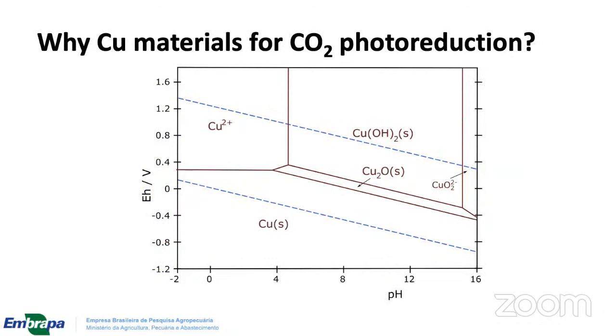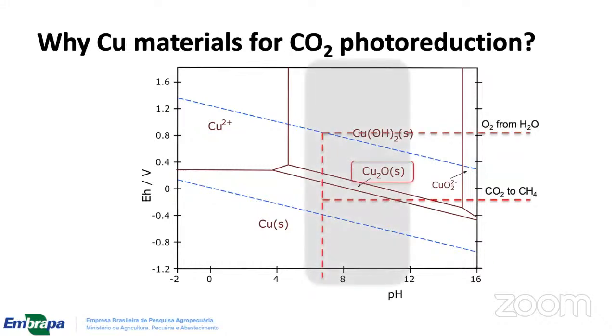Coming back to the copper oxides, the copper oxides are interesting even in that condition because we can think of them, as I said, as a kind of electrochemical cell in the same particle. These particles are submitted to a reduction potential when illuminated. This is the band gap, these are the requirements of the reaction. On one side, the particle will be submitted to a reduction reaction, the CO2 in that case, and the other side submitted to production of oxygen, thinking that we are doing the reactions in water, which means that the site where the oxygen is evolving is naturally in an oxidized state, whereas the site where the reduction reaction is taking place is reduced as copper.